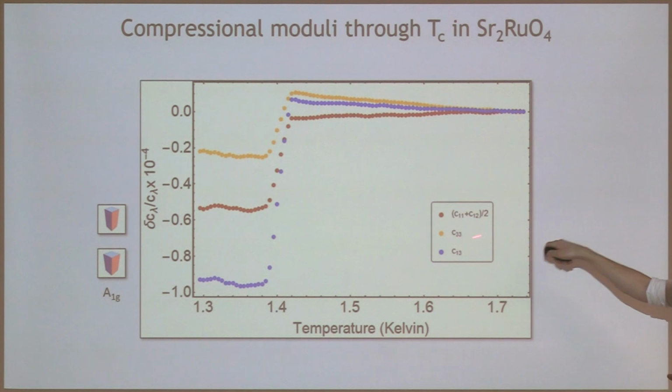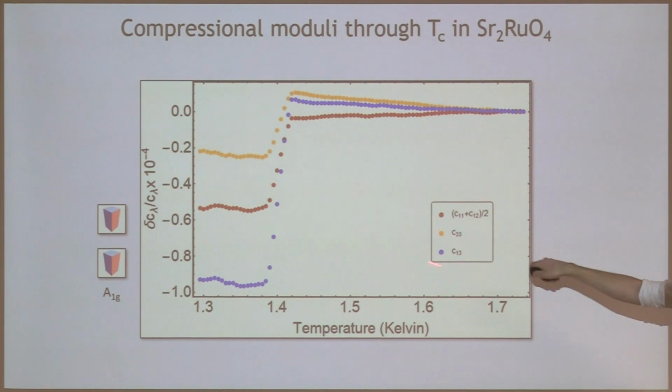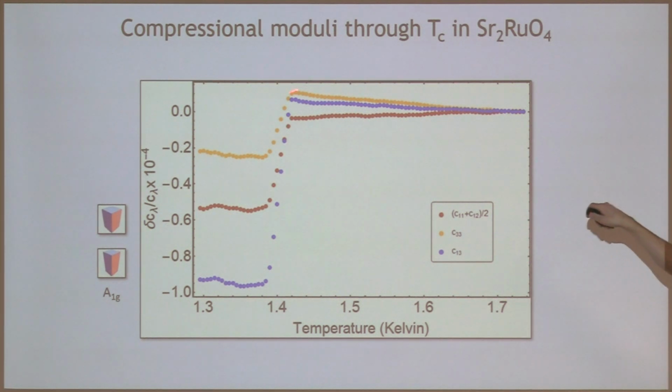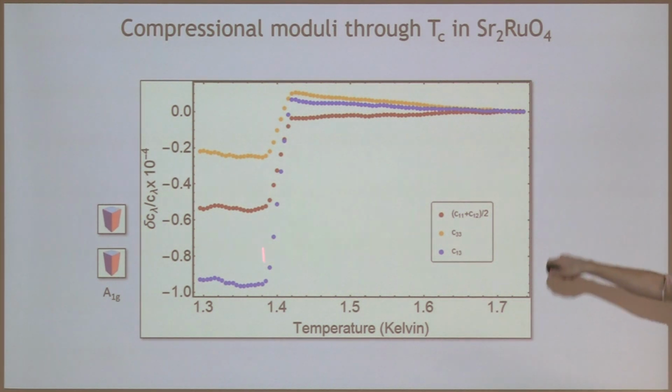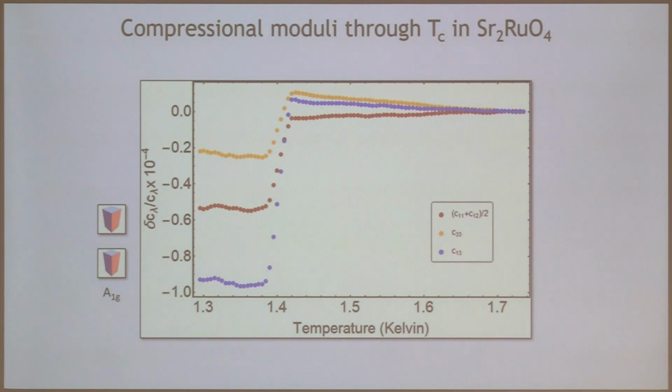There are two compressional moduli, and because they have the same symmetry, there's a coupling constant between them. And just so that we know we're not crazy, this jump times this jump should be this jump squared, and it is. So, 4 minutes, perfect, we're almost done. So we think we can at least measure the thing that has to be there for all superconducting phase transitions, so we know we're at least doing something right.